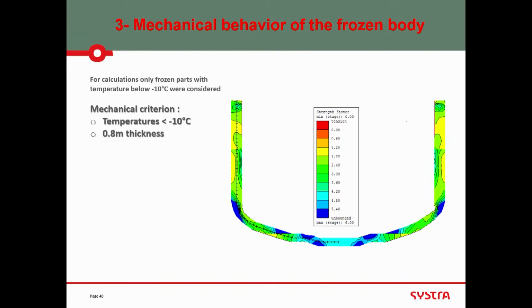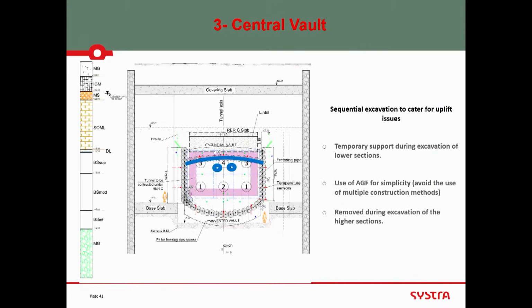We could have done something a little bit trickier, but taking more risk, because here we had stability for uplift. We could have decreased the temperature in this area, because this is just for water tightness, to -2 degrees. There are other projects where we did -2 degrees, -3 degrees, as we did in Paris for another station, to ensure just water tightness, preventing water from flowing into the excavation. The top for excavation was frozen to help phase stability.